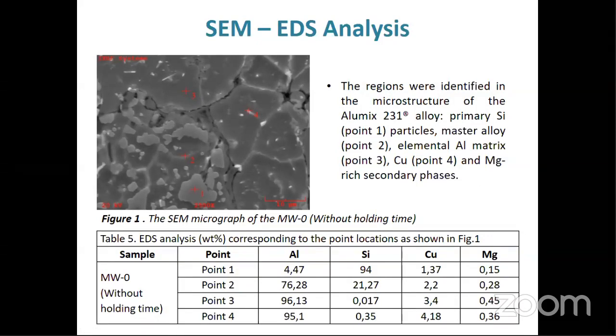Figure 1 represents the SEM micrograph of the sample MW0 sintered at 555 degrees without holding time, and the EDS results shown in Table 5 were marked in the figure as points 1 to 4. Point 1, light gray particles. It contains 94% by weight silicon in EDS results. These are primary silicon particles. Point 2, the region containing light gray particles is master alloy. Point 3, dark gray region, elemental aluminum. And point 4, fine bright phases, copper and magnesium rich secondary phases. EDS results in Table 5.